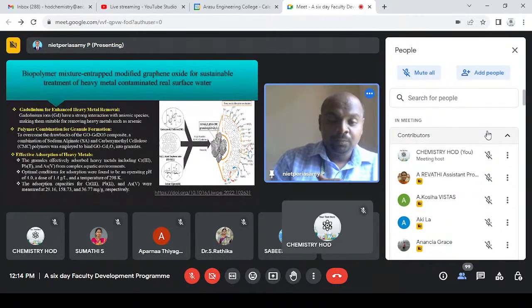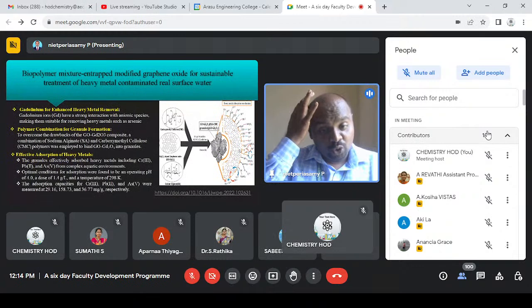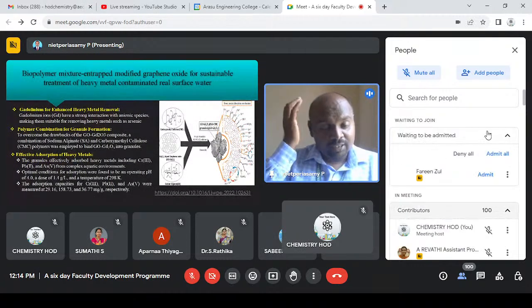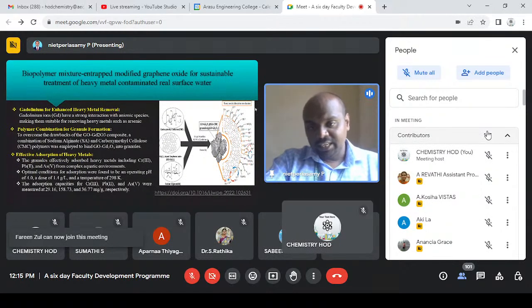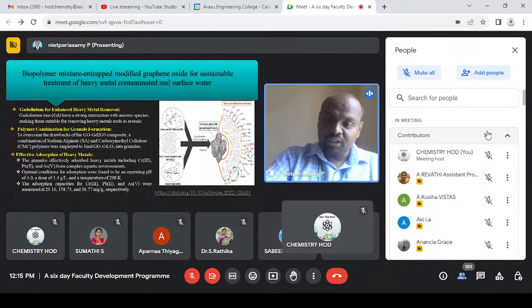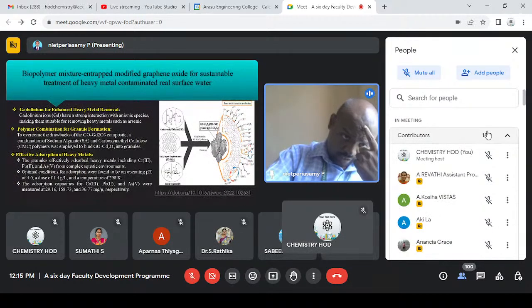so that they can come up with a new achievement. After the optimal conditions for adsorption were found to be an operating pH of 4.0, a dose of 1.4 gram per liter, and a temperature of 298 Kelvin, the adsorption capacities for chromium, lead, and arsenic were in the range of 21.16, 158.73, and 36.77 mg per gram respectively. So here on the right side I have shown the pictures. Each and every component was filtered out with the help of these graphene materials.